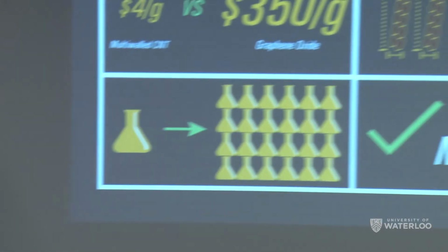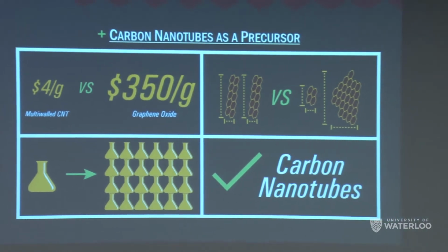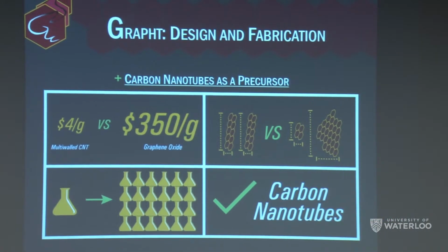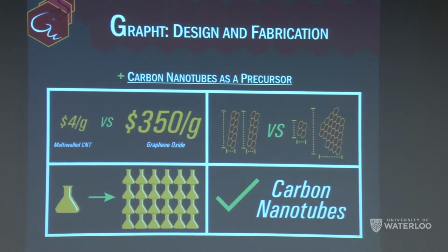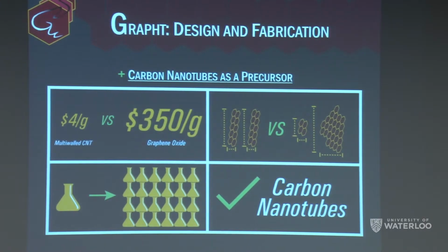So for the production of Grapht, we decided to use carbon nanotubes as a precursor rather than purchasing reduced graphene oxide or starting with graphene oxide from graphite sonication. One reason we chose carbon nanotubes is the price of carbon nanotubes as opposed to graphene oxide. There's a huge discrepancy. Multi-walled CNTs are $4 a gram, while graphene oxide that's purchasable and usually used as an additive is $350 a gram. So from the get-go, we have huge cost savings, especially if we want to scale up industrial use.